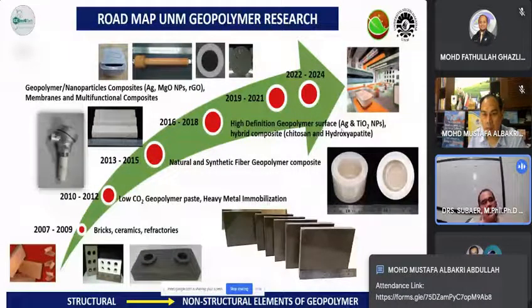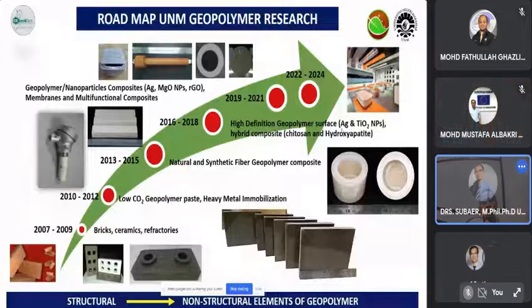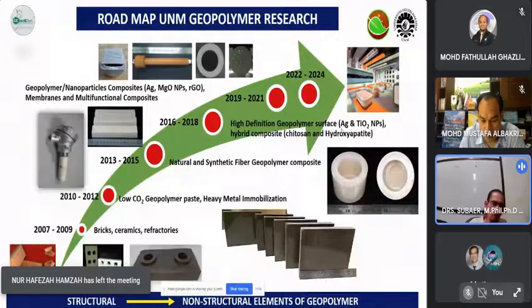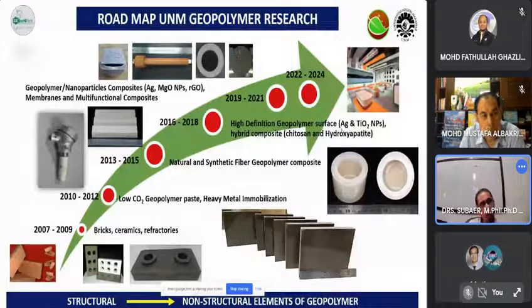We still remember that the refractory that we produced in 2007 or 2009 was able to resist fire with a temperature around 850 to 1000 degrees Celsius. So we feel that if we add the pure geopolymer with other inorganic materials, then we should be able to extend the temperature range of the refractories.